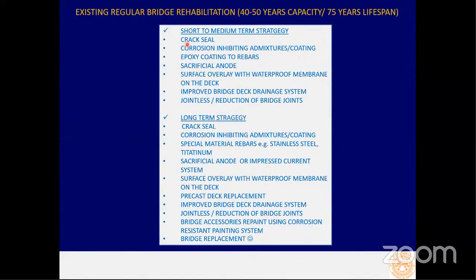For example, we do just crack sealing. We do the corrosion inhibiting admixture coating. We do some epoxy coating to the rebar, but we need to control the dry condition. We do some sacrificial anode or regular anode for the short-term protection. We can do some overlay on the top deck with waterproof membrane so that we can eliminate the water leakage from the top.